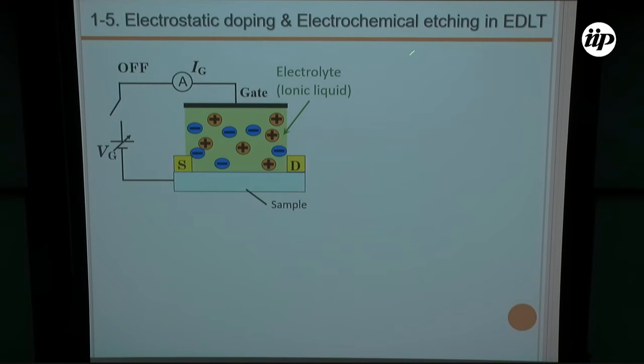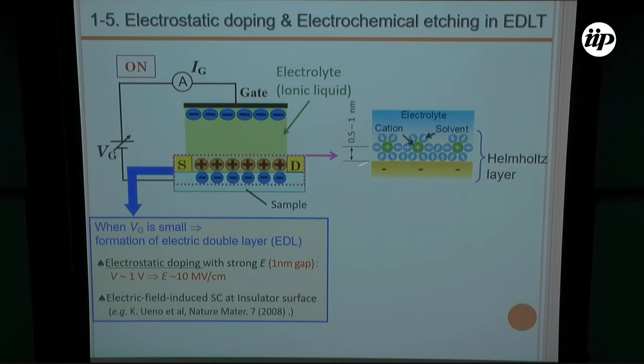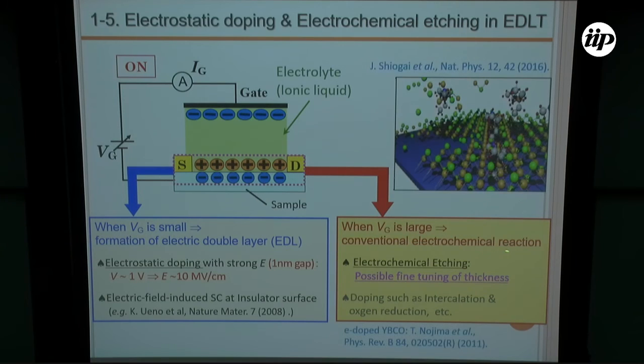EDLT is a kind of FET where an ionic liquid or electrolyte is used as the gating material. By applying a few volts, this can accumulate more than one order of magnitude higher carrier density than the usual FET. And this is the famous function of the EDLT, that is electrostatic doping. Okay. On the other hand, this EDLT device has another functionality, that is electrochemical reactions, when the applied VG is larger and the temperature is higher than the conditions of electrostatic doping. This electrochemical reaction contains many phenomena such as electrochemical etching, intercalation, oxygen injection and so on.